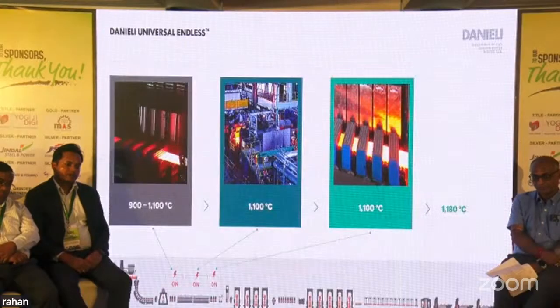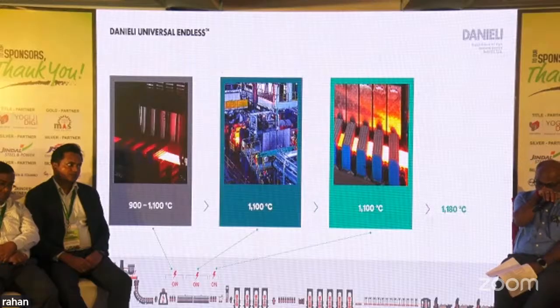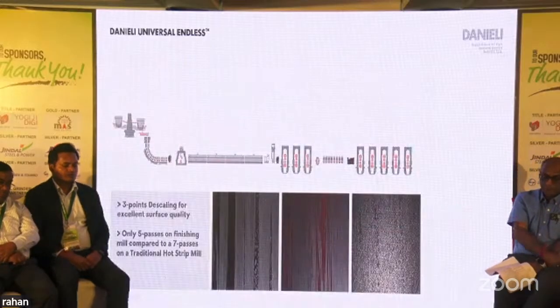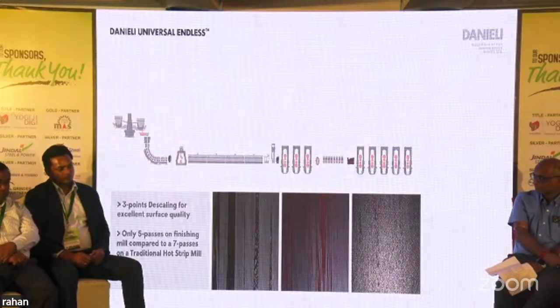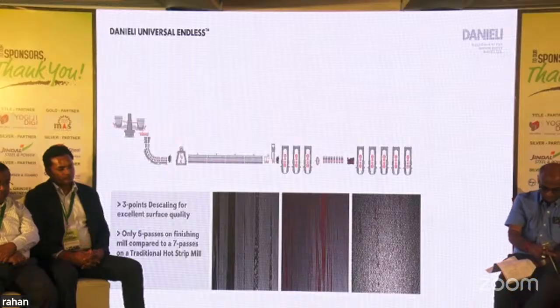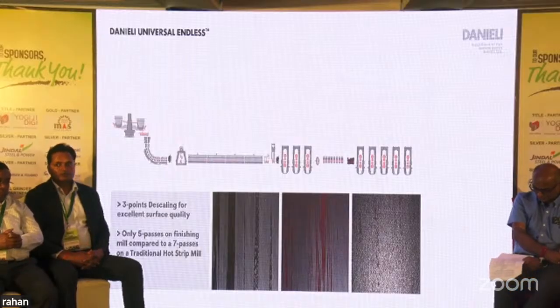Now, this one is interesting. The tunnel furnace has induction heaters in the entry and exit, so you can eliminate any kind of gas. Then, typically a conventional rolling mill will have 5 to 7 passes. But here you can have 5 passes and still get the right surface quality. So automatically your electrical consumption is less.